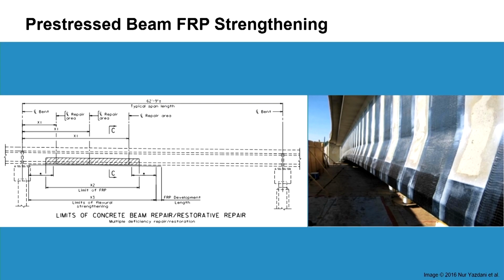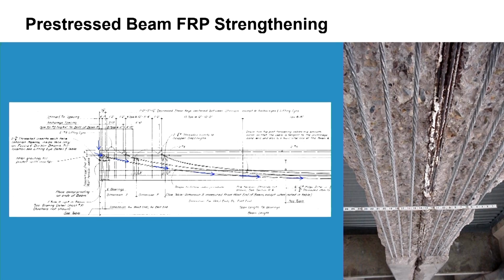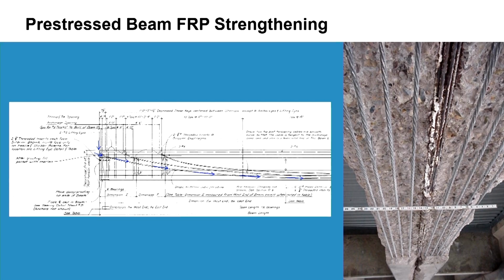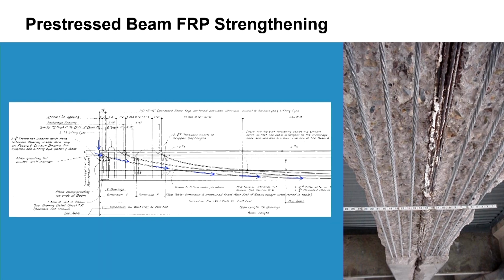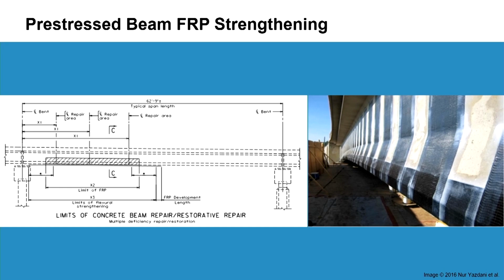And so in order to reintroduce the strength that was lost from that corroded post-tensioning, we will be adding FRP strengthening to the bottom of the beam. And then in addition to that, we'll be using discrete FRP wraps up the side of the beam to offer some confinement to that bulb, because if you see from the previous photo, there's no confinement reinforcing anywhere in this beam, so protect the public down below in case there's any further deterioration.